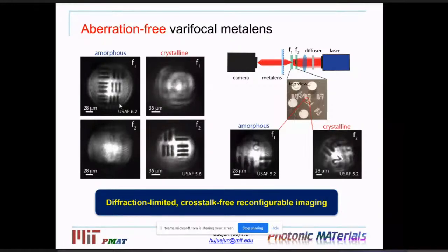And we also characterized the resolution of such a metalens, and we find that indeed it can achieve the diffraction limit, again indicating that we can realize aberration-free imaging using this kind of switchable metalens. So the takeaway message: we have now realized a reconfigurable material platform that can achieve different kinds of tunable photonic devices by implementing a phase change onto the chalcogenide compounds.